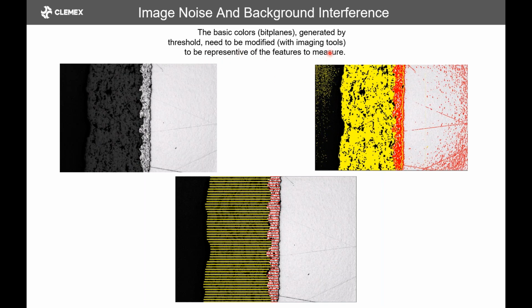Now, what we need to do here is to use some imaging tools, because when we're picking up this red line for the bond coat, we can see that the background, the substrate, is also being detected. So we have some scratches and all. We have some tools that will get rid of these things. And as you can see, we end up with a proper detection of the coating.